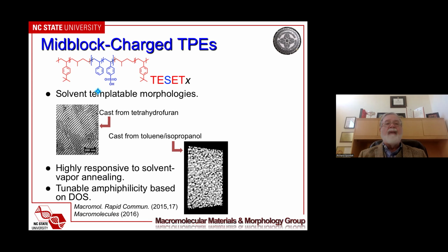The intermediate blocks are hydrogenated polyisoprene, otherwise known as ethylene propylene rubber, denoted here by E. And this is what gives the material flexibility. And then the middle block is partially sulfonated polystyrene, S. And the red units that you see here are hydrophobic. The middle block is hydrophilic. So this is, in fact, a thermoplastic elastomer. It does have elasticity associated with it. And I will point out that in addition to referring to this as TESET, we're going to put an X after it to denote the degree of sulfonation.